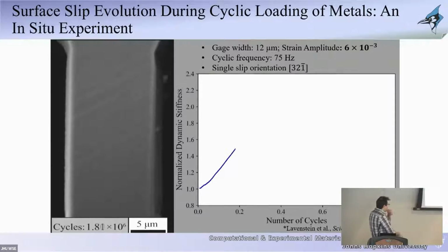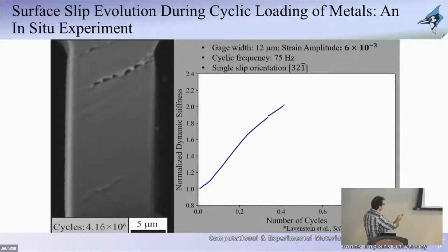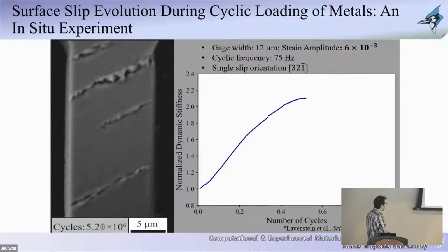What I'm showing you on the plot over here is something called the dynamic stiffness. This is a measure that you get from the nano indenter as you do these experiments. It relates to the stiffness of the material. It's not a direct measure of the stiffness of the material, but it relates to that stiffness. And what is intriguing as you do these experiments and as you reach about 3 million cycles, you start seeing this deformation forming on the surface. There's defects that form on the surface. It's an extrusion and an intrusion, and it starts to propagate. And it's not only one, there's multiple ones that start popping. You'll see continuously all these background lines that show up. You'll see some of these forming, nucleating, propagating along those specific lines.